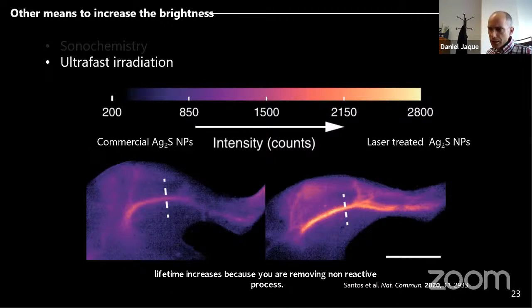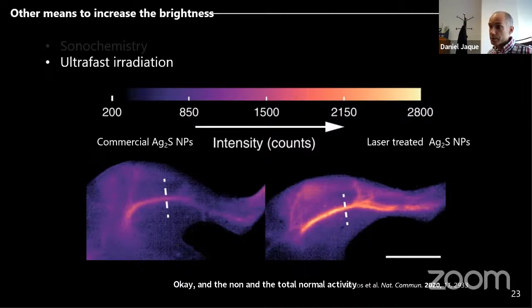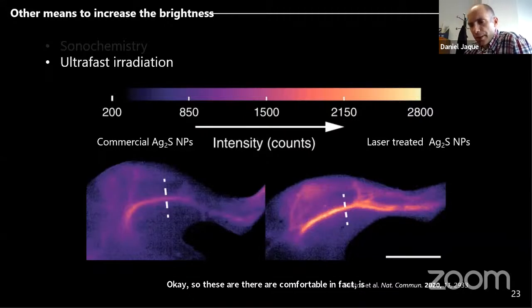And the total non-radiative decay rate is smaller, and because the lifetime is 1 over the total decay rate, the lifetime increases, okay? So they are compatible. In fact, it's what we were expecting. When you increase intensity, you expect to have some increment in the lifetime. Very good, thank you very much.